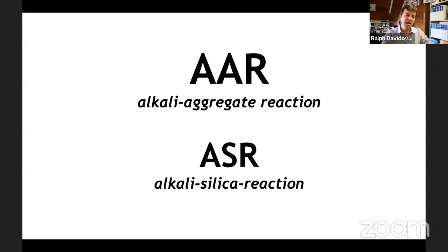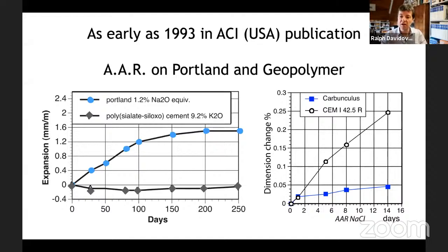Despite the fact, proven since 1993, 28 years ago, by several studies, that the geopolymer chemistry is very different from Portland chemistry, for Portland cement, where alkali is handled very differently. Here is a simple example. We have the calculation of the alkali aggregate reaction on Portland and geopolymer cement. On the blue line, blue spot, we have Portland with 1.2% of Na2O equivalent. And in gray, we have geopolymer cement with 9 times more K2O. And you see, after 250 days, there's no expansion, nothing is happening, whereas with Portland cement, there's a small expansion, which yields alkali aggregate reaction. There's nothing like that with geopolymer cement.